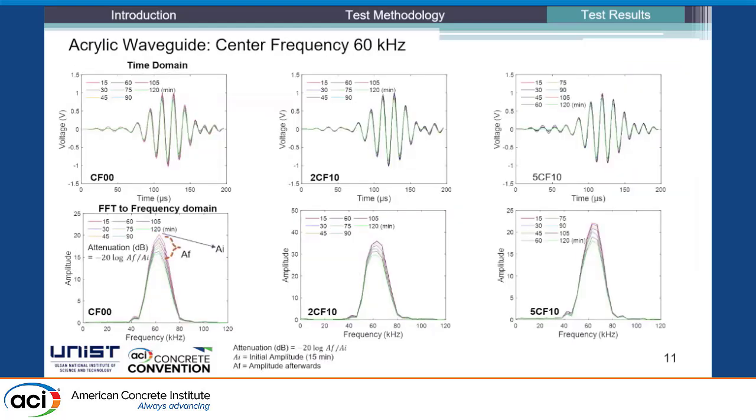And next, moving on, we have the acrylic waveguide with 60 kHz center frequency. And you can see from the graphs here in the frequency domain that there is a decrease of energy over time from 15 to 120 minutes. And I forgot to mention, we did this test for 2 hours right after casting.